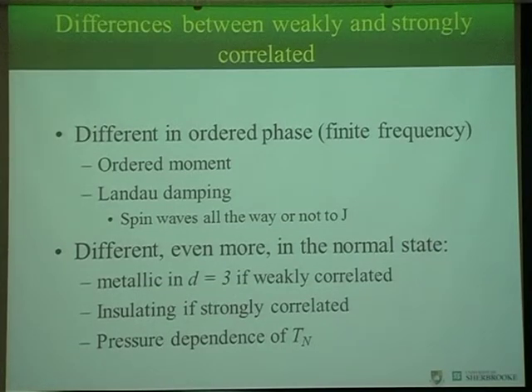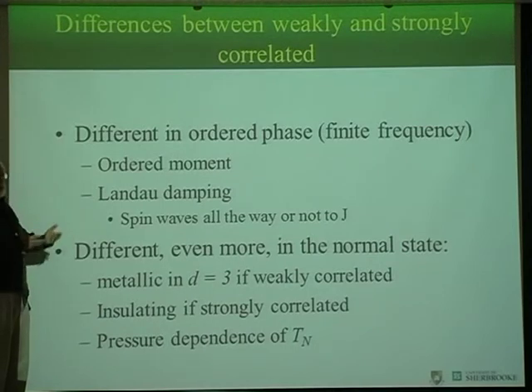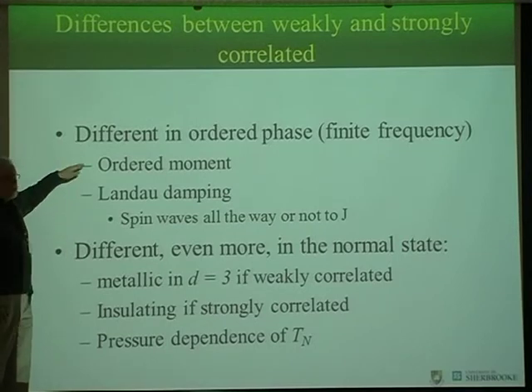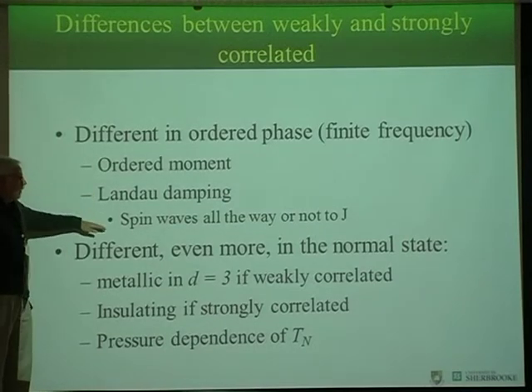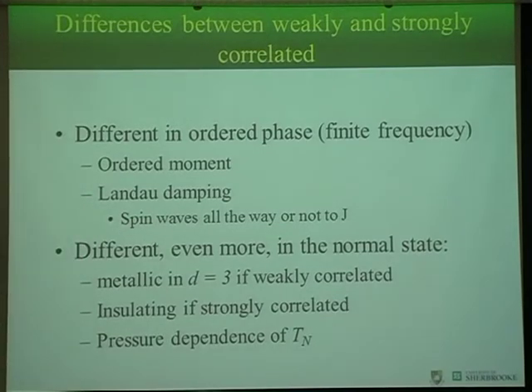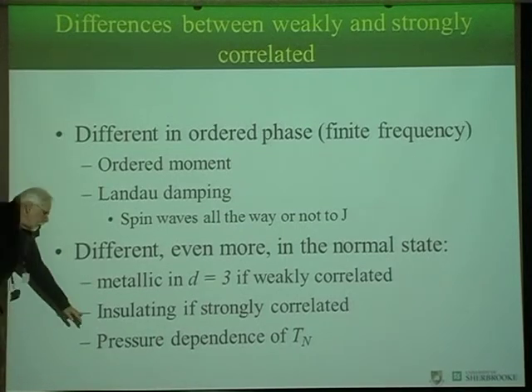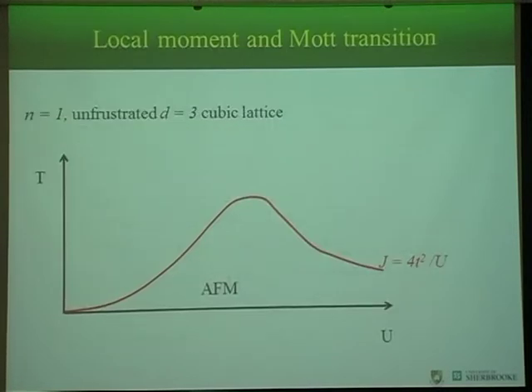But if you look now, there's a difference whether the antiferromagnet comes from a Mott insulator or it comes from an ordinary metal. If it comes from an ordinary metal, it's called an itinerant antiferromagnet. Otherwise, it's called just a Heisenberg antiferromagnet. The differences can be seen like this. Both of them have spin waves. All these emergent properties are there, but the ordered moment will be different. The Landau damping will be different. The spin waves will go all the way to J if you're in a Heisenberg model, but not if you're in an itinerant system. And in the normal state, they're even more different. In 3D, they're metallic if they're weakly correlated, or insulating if strongly correlated, and the pressure dependence of the Néel temperature is different.